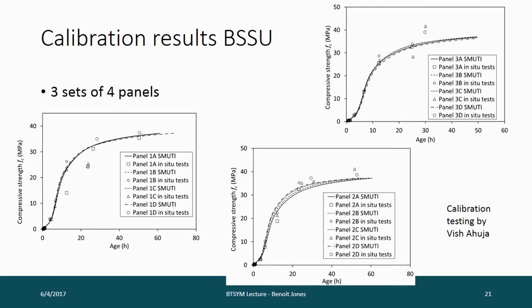So here we've got the 3 sets of 4 panels, and the smooth lines are the SMUTI, and the individual points are from penetrometer, Hilti pull-out tests, and also coring at later ages. And we've gone up to 50 or 60 hours, and it's pretty good agreement, but you can see how much scatter there is in the results from the strength tests. And if you look, for example, at that one on the top right, and you look at the triangles,